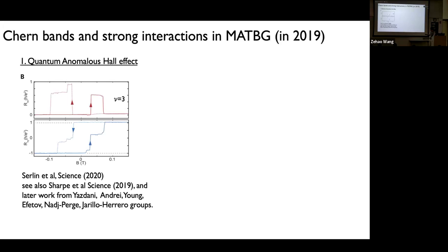And I think 6 months later, there was this experiment, again from Andrea Young's group, where they indeed took twisted bilayer graphene and tried to align it with HBN. And then at the moiré filling of 3, they observed this quantum anomalous Hall effect, which is a strong evidence. It's basically telling you that the system is really described by Chern bands. And then because of electron-electron correlation, you can basically stabilize a Chern insulator. And later that summer, 2019, there were a series of works that were mentioned also yesterday, where if you apply a small magnetic field, you can also stabilize a similar state.